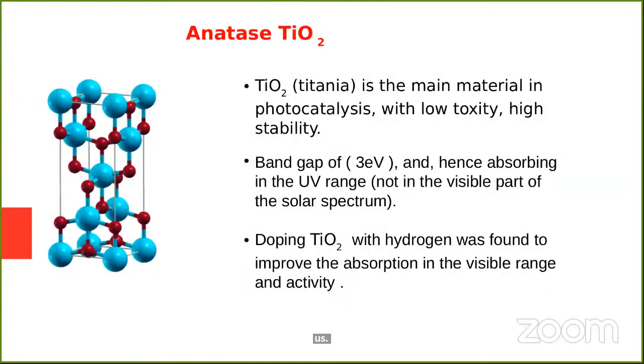A possible solution using solar energy to produce a chemical fuel is known as the photochemical method. And one important part of the photochemical method is a photocatalyst. In photocatalyst applications, the standard material of choice is titanium oxide, for its wide range, low toxicity, high stability, and wide activity. Among titanium polymorphs, anatase is found to have the highest efficiency for photocatalyst application, and also has a band gap around 3 electron volt and absorption in the ultraviolet range, but not in the visible range. Doping titanium oxide with hydrogen was found to improve absorption in the visible range and activity.